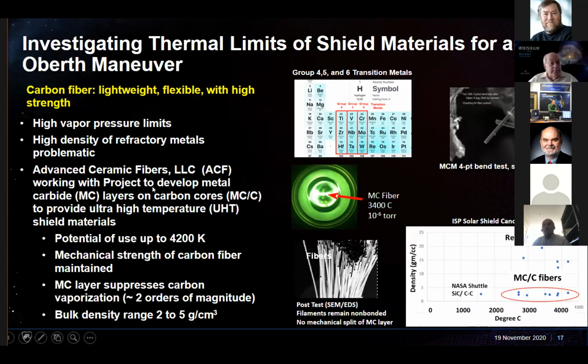A big part of that effort has been trying to get things to high temperatures, and we have some idea that we're getting things up above 3,000 and surviving in a metal carbide fiber. There are densities here where you can potentially operate in this lower density regime, which is good from a shield mass point of view. You're doing it in such a way that you keep some of your mechanical strength of the carbon. How much you're keeping is a big question.